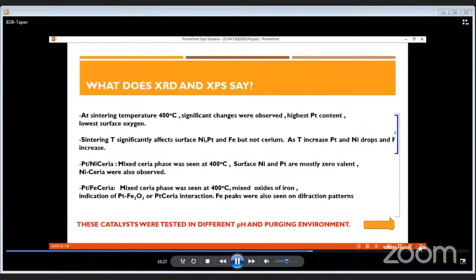So, what do XPS and XRD say? At the sintering temperature of 400 degrees, significant changes were observed, and the highest platinum content and lowest surface oxygen was also seen. Sintering temperature significantly affects surface nickel, platinum, and iron, but not cerium. As temperature increases, platinum and nickel drop, and iron increases.